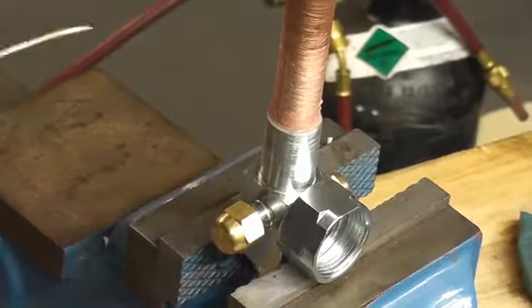You see the flux dried right up there and turned into a paste, really chalky. As I heat it up more, then it'll turn into a liquid again. And you can see it start to bubble and liquid up, and you can see where the flux is working. Alright, that's just starting to turn red. I'm going to move my heat down to the steel. And that's going to heat up. You see that start to turn cherry red? And they're all nice and red together.